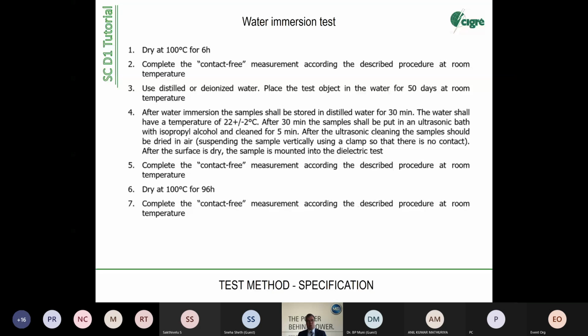What is water immersion? So we dried the samples first at 100 degrees for 6 hours. With contact-free measurements, we want to measure. We use distilled or deionized water and place the test object in water for 50 days at room temperature. You can even promote the aging if you increase the temperature. So there's a rule: if you increase the temperature by 10 Kelvin, according to Arrhenius, you get double the process behind. So if you have a diffusion mechanism that depends on this equation, then by an increase of 10 Kelvin, you double the speed of diffusion of water into the material.